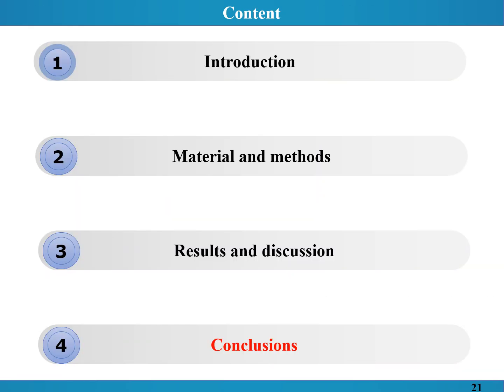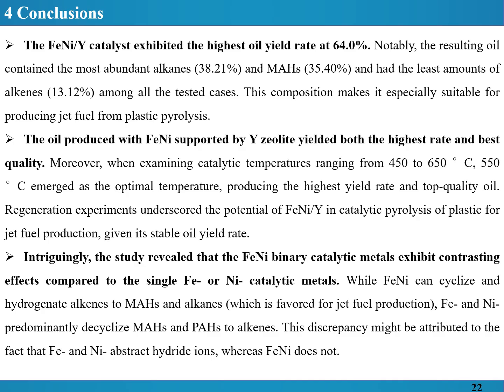The fourth part is the conclusion. The iron-nickel doped Y zeolite catalyst exhibited the highest oil yield rate at 64%. The oil produced with iron-nickel supported by Y zeolite yielded both the highest oil yield rate and the best oil quality. The study revealed that iron-nickel binary catalytic metals exhibit contrasting effects compared to the single iron or nickel catalytic metals.